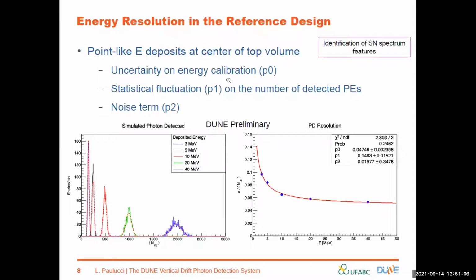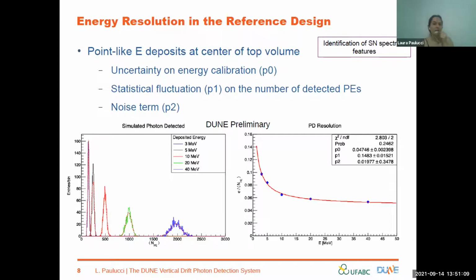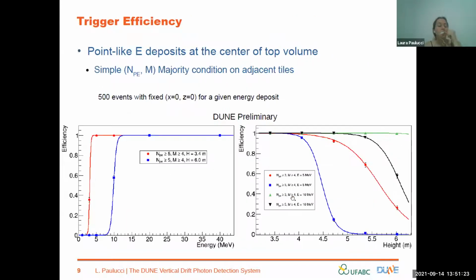One more minute. Okay. We have also made energy depositions, so energy resolution that we can see here that we can get better than 10% for energy depositions of 3 MeV. And also we have analyzed a preliminary trigger efficiency that we could get, using a simple majority condition on close tiles. And this is for events happening at the center of the volume and increasing distance to the cathode. And here for different energies.